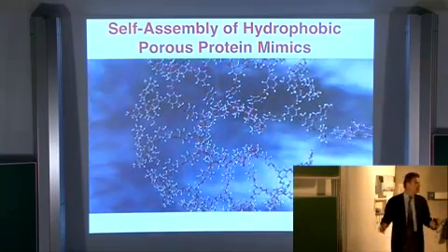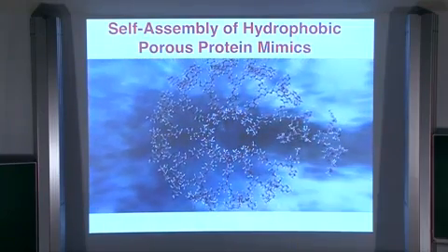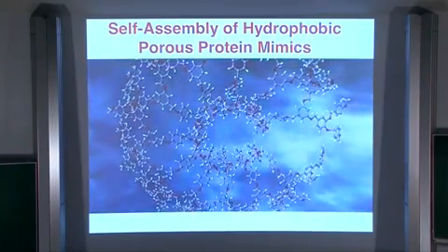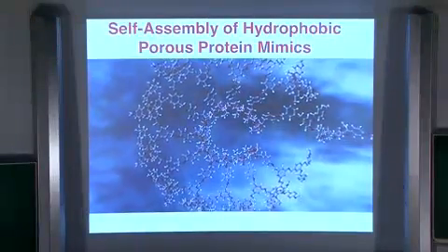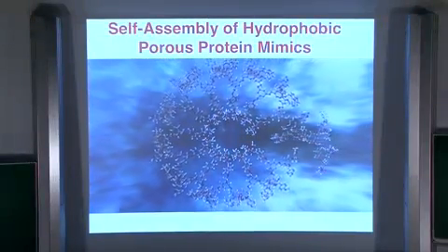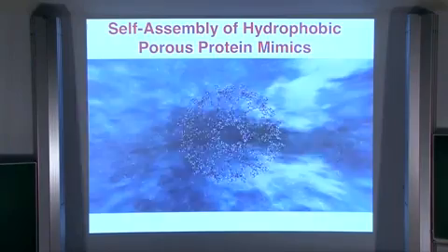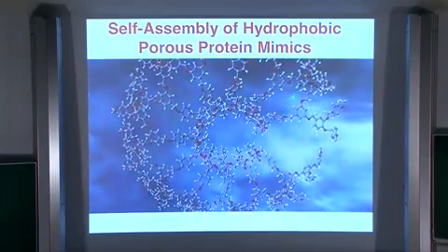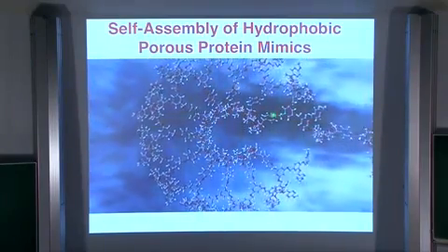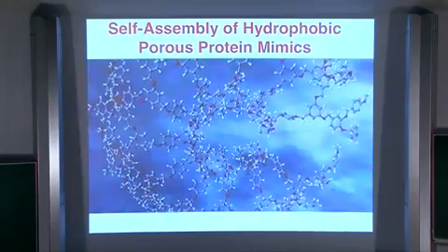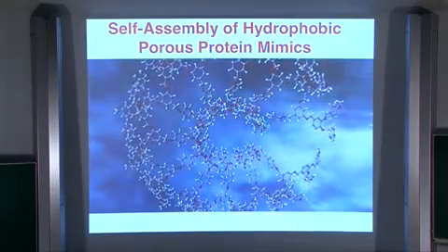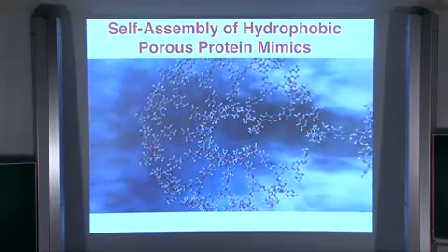I'm not going to spend time describing that, but here is the structure that was solved by X-ray diffraction experiment. And the cartoon just shows how the molecules are coming together and what we could not learn from the analysis of the individual molecule. So you see that all is trans conformation of the dendron. The dipeptide is orthogonal to the dendron. The molecules come together and they cannot fill this empty spot in the middle.